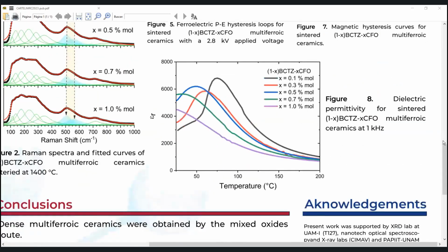When carrying out the dielectric analysis of the materials, the curves of figure 8 were obtained, where different behaviors are observed for each sintered ceramic. In general, the decrease in the dielectric transition temperature is notable. This indicates that the orthorhombic ferroelectric to cubic paraelectric phase change of the material occurs at lower temperatures as the proportion of dopant increases. In turn, higher amounts of dopant cause lower values in the maximum dielectric constant of the materials, and a phase transition with an increasingly diffuse behavior.